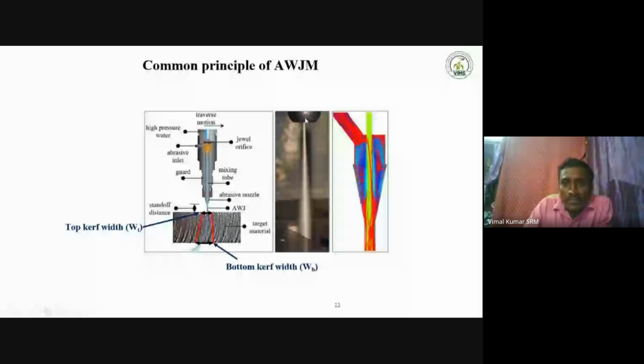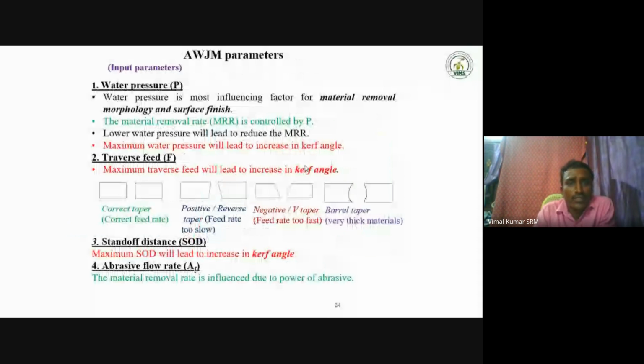This one is the nozzle. The nozzle produces high pressure water. The high pressure water is mixed with abrasive. In this condition, it can cut high strength materials. So these are the water jet machine parameters: water pressure, traverse speed. When the traverse speed is changed, several kinds of cut surface are identified. The first one is the correct taper. The second one is the positive or reverse taper. The third one is the negative or V taper. The fourth one is the barrel taper. If the water jet machine parameters do not fit the material, we can get the second, third or fourth kind of cut surface. If we choose the correct cutting parameters, we definitely get the correct taper in the cut surface.